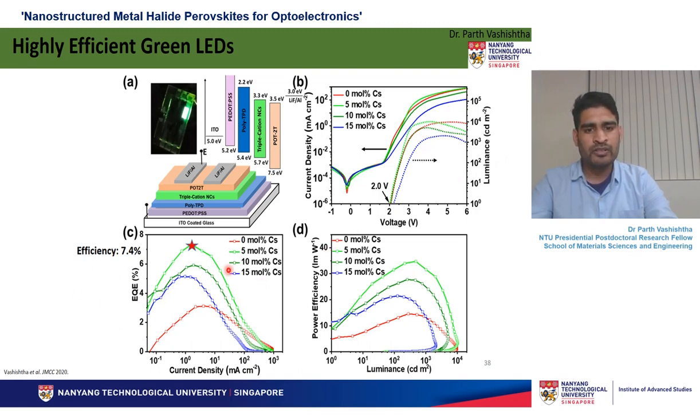and the external quantum efficiency was also highest for 5% cesium, which has more cesium on the surface. The highest EQE, external quantum efficiency, was 7.4%. These LEDs showed great power efficiency as well, about 35 lumens per watt.